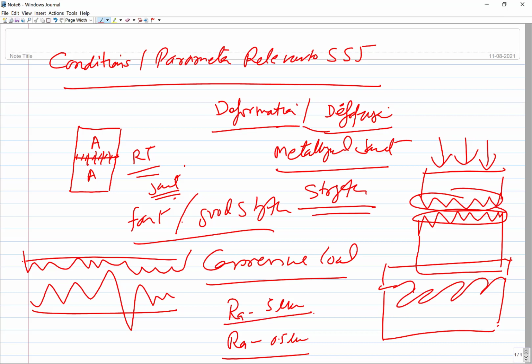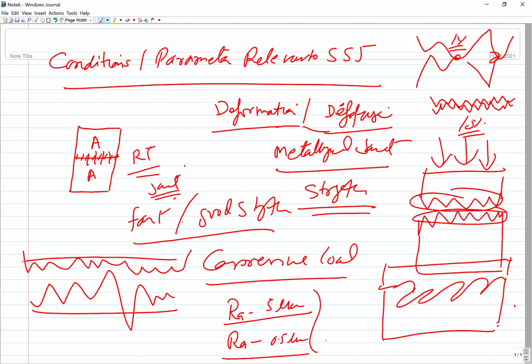Anybody can respond? The first one, very good. When you have larger or deeper and higher peaks and valleys, using somewhat lesser load you can make them deform and come close to each other. But when you have a finer surface, there is a possibility that they are already very close to each other, as compared to the case when they are far away and the local contact is here and there. In this case, the contact may be just 1% of the apparent area, and here it may be 10% of the apparent area.